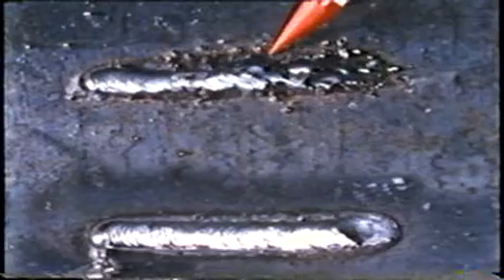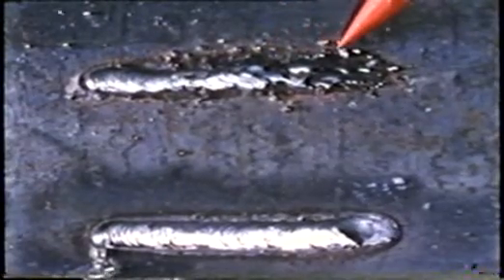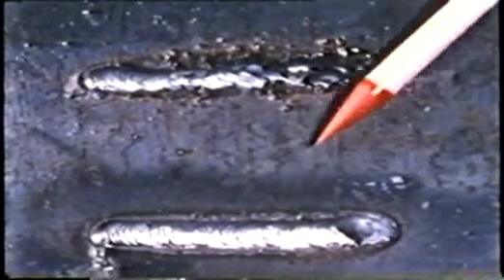Even if the welder is set at the recommended current setting, another poor weld will result when the arc length is too long. Metal melts off the electrode in large globules, resulting in severe spattering. In addition, poor penetration will occur. The result is quite obvious when comparing it to the correctly made weld bead.